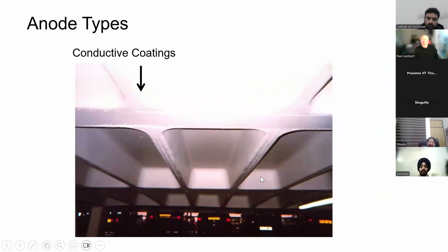On lighter structures, it's possible to use conductive coatings. This is a waffle slab in a car parking garage. It says conductive coating. You can't see the conductive coating. It's black. It's carbon based. It's painted white for obvious reasons. Not good lighting if you've got it black. Also, the coating on top protects it from moisture damage. There are wires that run along, and the coating's been placed over that to distribute the current.